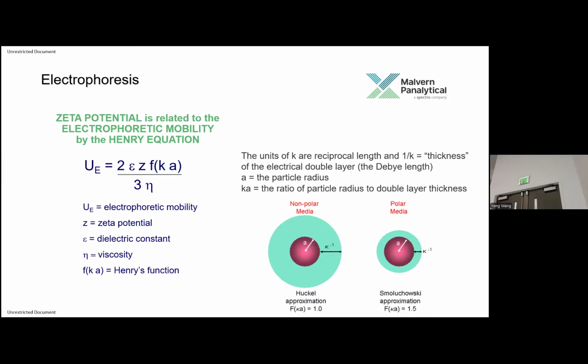Right? And when you are talking about sample preparation, let's say you simply put polymer nanoparticles in a buffer. If you need to dilute down your sample, you need to dilute it down in buffer. So if you take your particles in the buffer and dilute it down in water, then guess what? You're diluting out your salts. And that's going to affect the electrostatic environment around your particles. So you need to be mindful of how you're doing it, because it's always the interaction between the particle and the dispersion. You have to consider both parts of that equation.